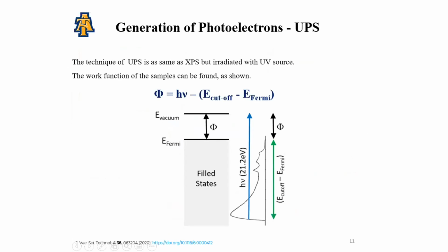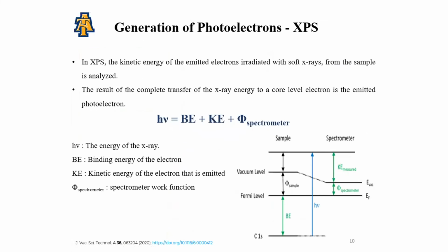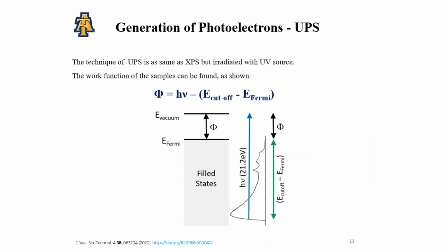Working of XPS. In XPS, the kinetic energy of the emitted electrons from the sample irradiated with soft X-rays is analyzed. The result of the complete transfer of the X-ray energy to a core level electron is the emitted photoelectron. The working of UPS is similar to XPS but irradiated with a UV source. The work function of the material can be evaluated using UPS.